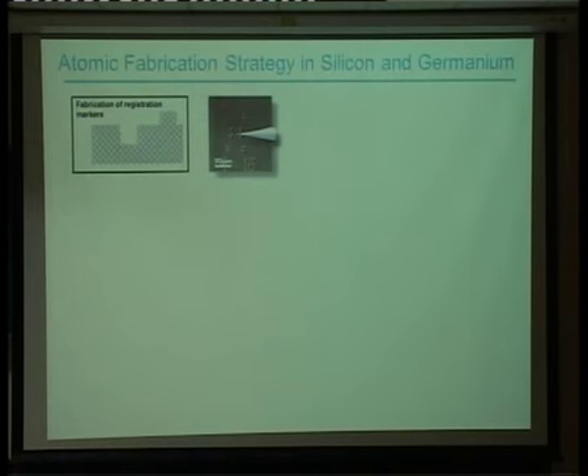The second challenge is it's not actually easy to manipulate atoms in silicon using a scanning tunneling microscope. You can't pick atoms up and place them somewhere else, as you would have seen in the quantum corral structure. The covalent bonds are far too strong, so you actually have to make an atomic resist and then create a template with the STM where you can open up holes on the surface and then use those as a template to put your phosphorus atoms in.